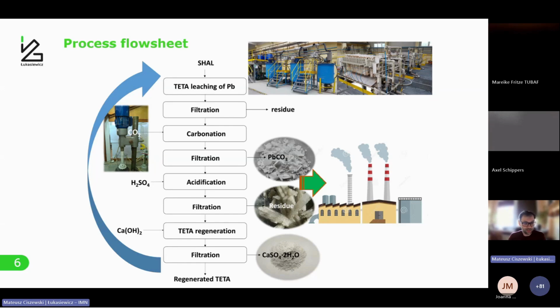Then we have filtration, so the other materials are left behind. Then carbonation. If you purge CO2 gas through this solution containing amine with lead sulfate, you will obtain lead carbonate, which is the main product of the technology.